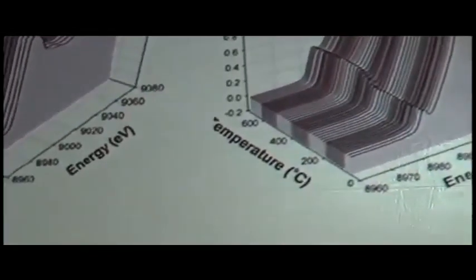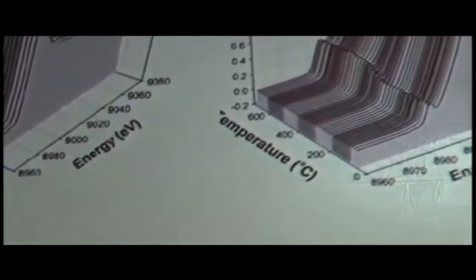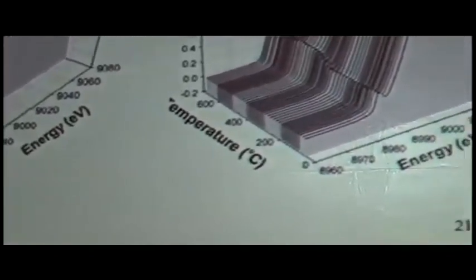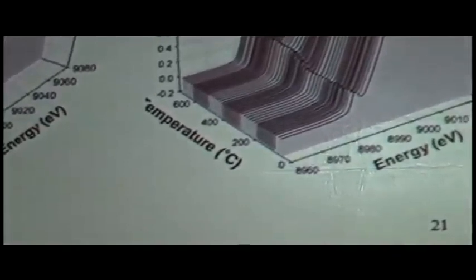But there's definitely a dramatic change in the XANES spectrum as a function of temperature there. I didn't point out that the y-axis there is the temperature of the catalyst going from right to left there. So probably can't read it from the very back at all. The pictures do tell a little bit of the story, but the nice thing about this is we can actually quantify the amount of various components here.